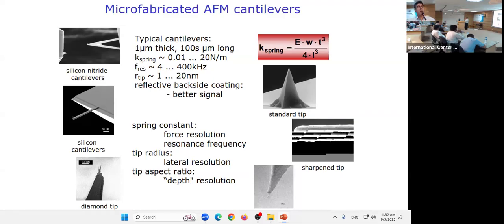So the thinner the cantilever, the better the resolution. But the problem is that the thinner cantilever breaks easily. It breaks very quickly. And another disadvantage is that when you are aligning your laser on the surface of the tip, that alignment is also difficult on the thinner cantilever compared to a thick cantilever. So these are the considerations, but it depends on what you are using. The thinner cantilevers are more expensive. The thick cantilevers are comparatively cheaper.